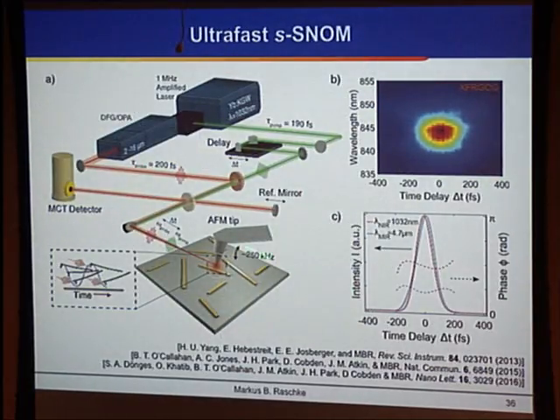So we really combine the scanning probe system, the way we do the near-field imaging, with the ability to have an intense pump pulse, and then we have a probe where we probe the response, the emergence of these metallic phases.